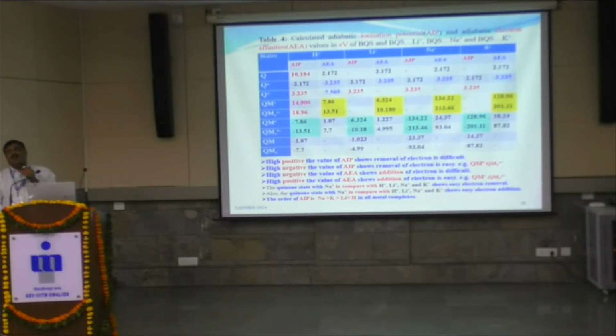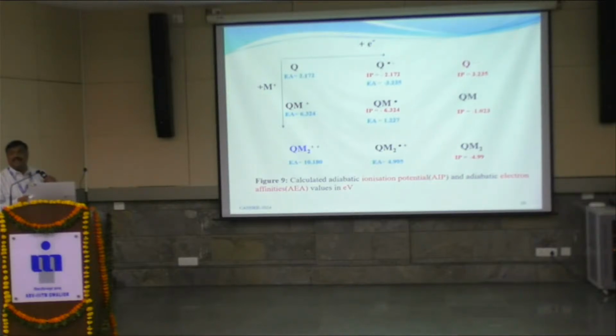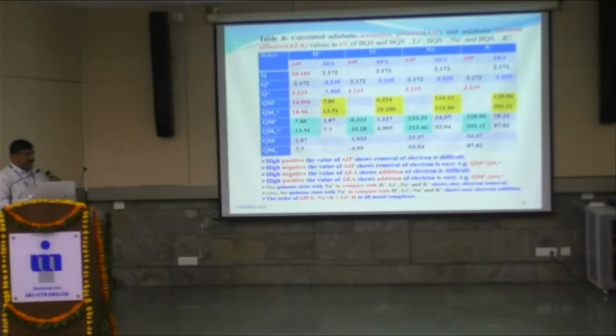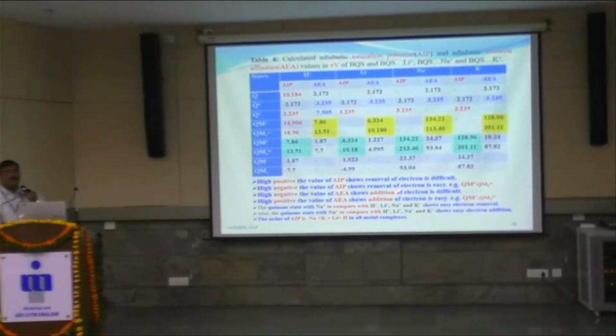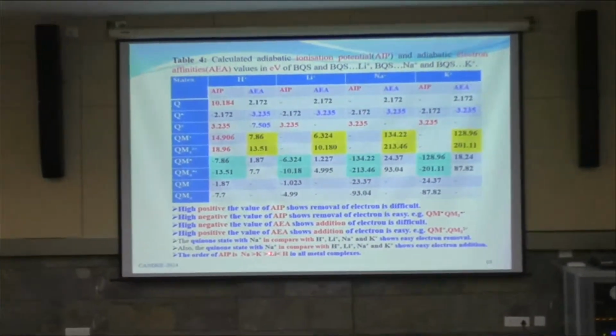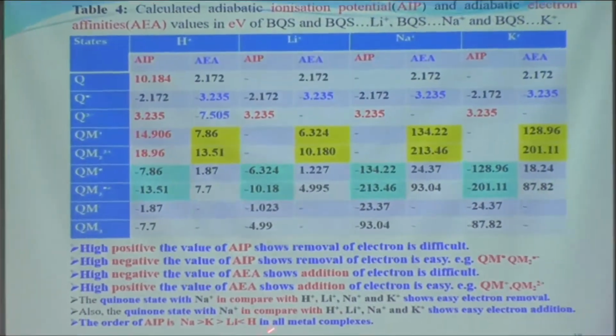In comparison with the previous binding energy calculation and the rho BCP and del square rho BCP calculation, these values are quite different. That is, for the quinone state with sodium ion, if we compare binding energy with hydrogen ion, lithium ion, potassium ion and sodium ion, it shows easy electron removal as compared to this binding energy. From the sodium complex we can remove an electron more easily, and also we can add an electron to that complex more easily. But the trend observed here is slightly different. If we compare the previous trend and this trend of adiabatic ionization potential values, it is slightly different. Sodium is higher than potassium, potassium is higher than lithium and hydrogen.